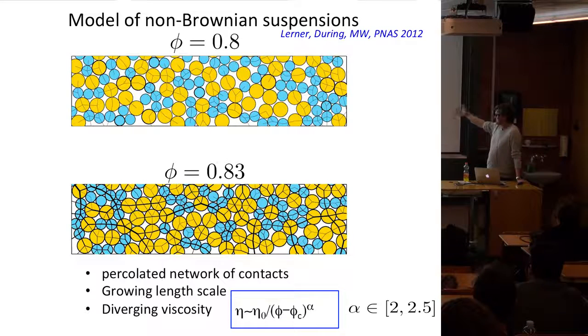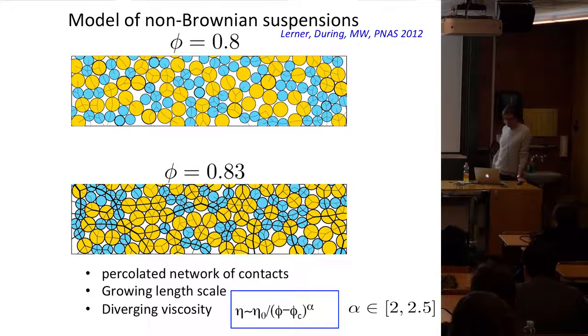What you can do, in numerics and in experiments, and it has been done by many authors, is to also look at rheological properties, not just kinetic, but also how, for example, a suspension has an overall viscosity. You have the viscosity of the solvent, but when you add more and more particles, the viscosity grows. And in fact, here it's going to diverge as you approach jamming, and it diverges with some non-trivial exponent. Okay, so the point is that this case, dense granular flows, seem to behave like a continuous critical point, where you have a diverging length scale and a non-trivial exponent characterizing, for example, rheological properties.